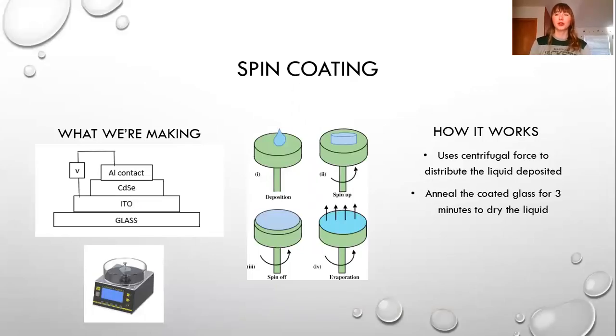So to make a solar cell, we do spin coating. In this first image, in this layered section, this explains what we're actually making. So we have glass that we've pre-ordered, and it's a layer of glass with an ITO layer, which is indium tin oxide, but it's basically just a conductive layer. And on top of that, we put our cadmium selenide quantum dots, and then later we'll go over how we actually put our contacts and wires on. And then this voltage travels between the aluminum contact and this ITO glass through our quantum dots.